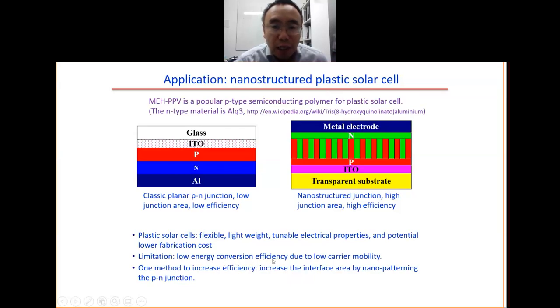But the problem for the plastic solar cell is the energy conversion efficiency, which is low. Normally it is well below 10%. For the classical silicon solar cell, you get about 20% energy conversion, but for the polymer solar cell, you get below 10% conversion efficiency. So how to improve this? This can be done by nano-patterning the p-n junction.